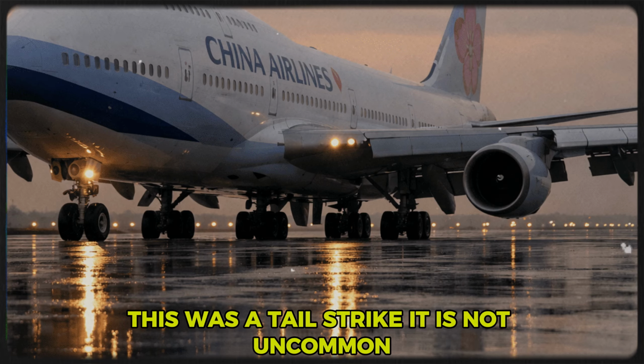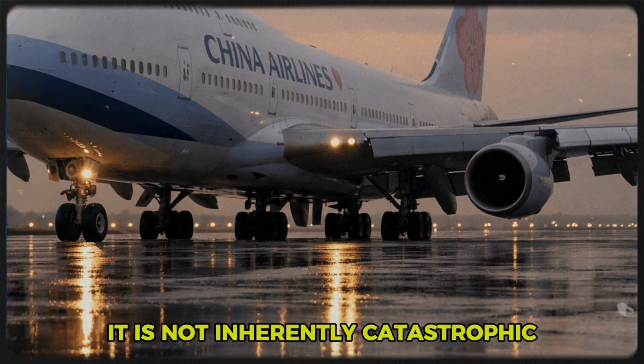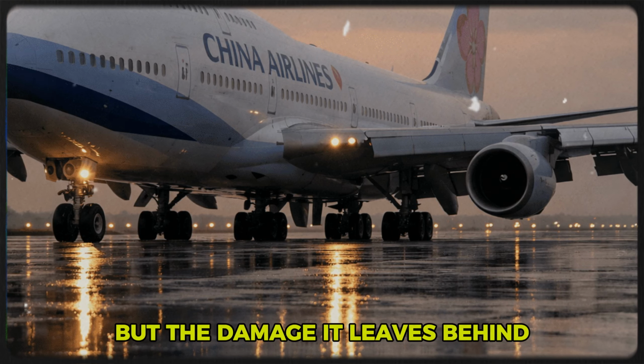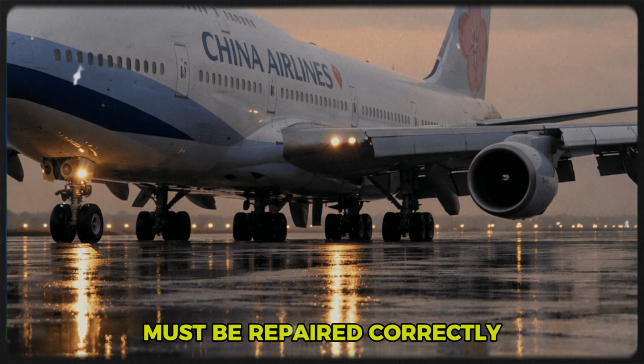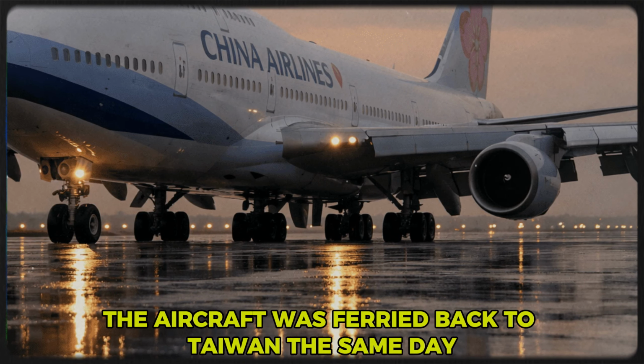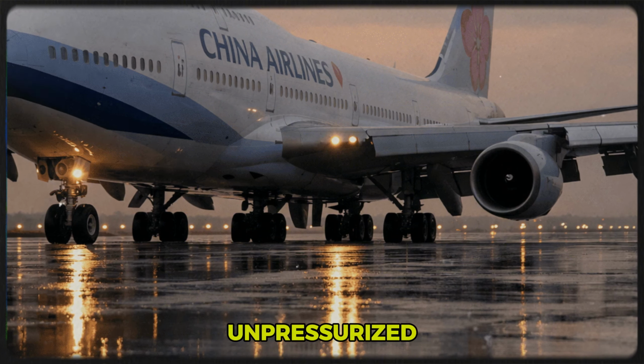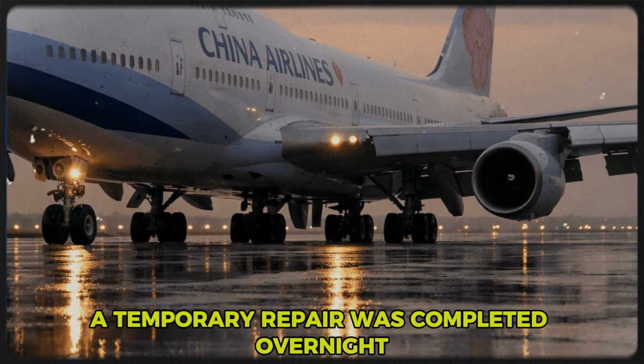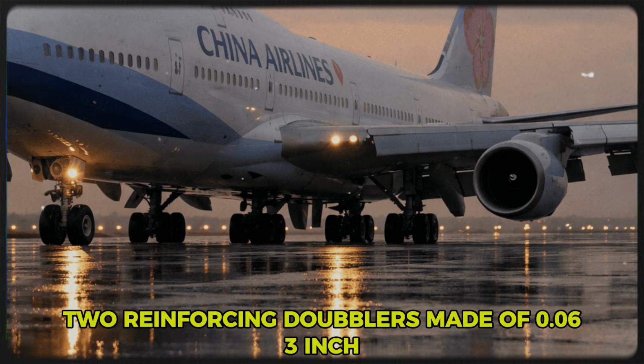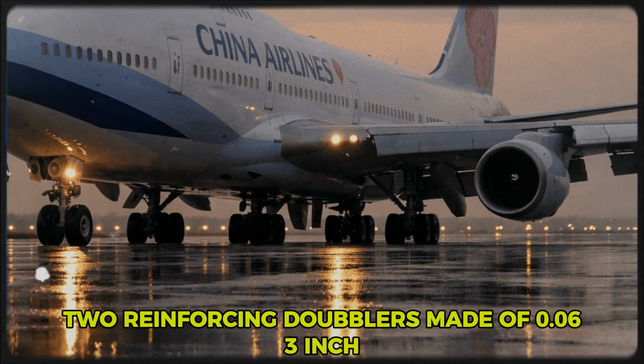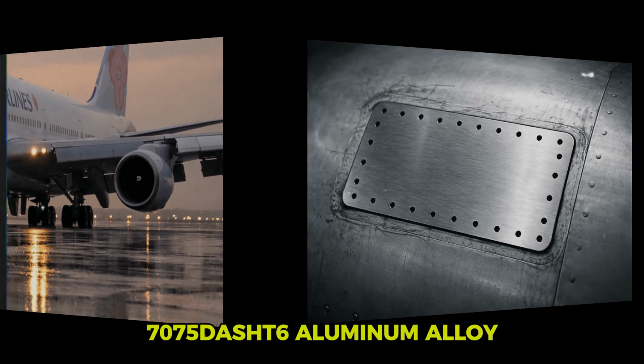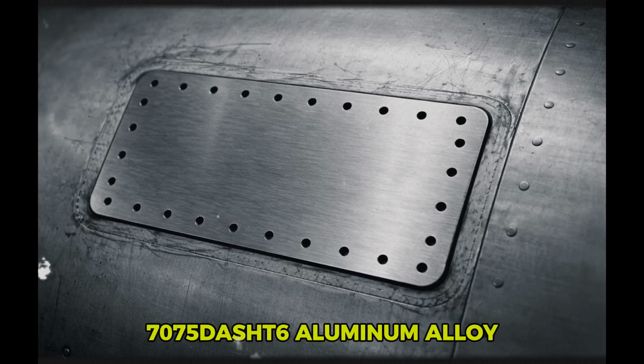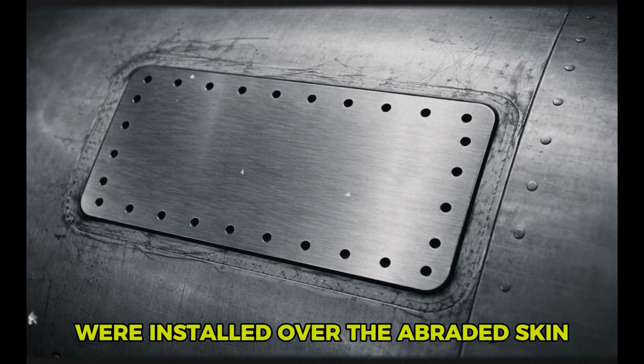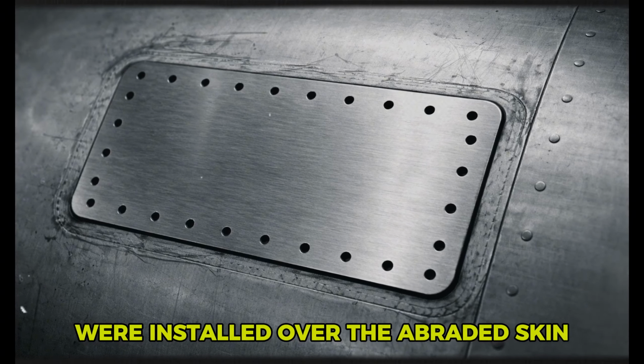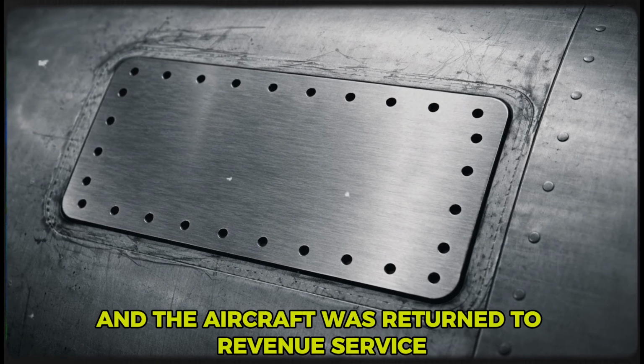This was a tail strike. It is not uncommon. It is not inherently catastrophic, but the damage it leaves behind must be repaired correctly. The aircraft was ferried back to Taiwan the same day, unpressurized. A temporary repair was completed overnight. 2 reinforcing doublers made of 0.063-inch 7075-T6 aluminum alloy were installed over the abraded skin, and the aircraft was returned to revenue service.